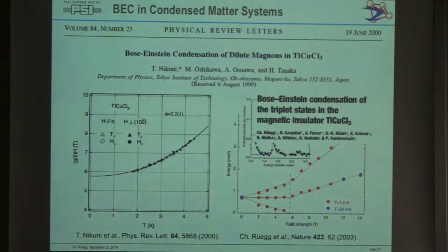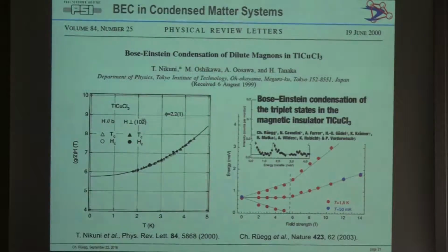What's the order parameter? That's just physically. The order parameter is that the spins on the dimer, because the field is on, you get an effective XY Hamiltonian. What you order then is the spin direction in this XY plane. Which is kind of like a canted antiferromagnet in a way. It is like a canted antiferromagnet, has a uniform component, but the order parameter is the transverse moment which orders. Néel order within the plane? Yes, that's right. The phase coherence is done by this long-range Néel order. Exactly. There's this literature which is now nearly 10 years old or so, where this is all discussed in detail. Do you know how large the anisotropy is within the